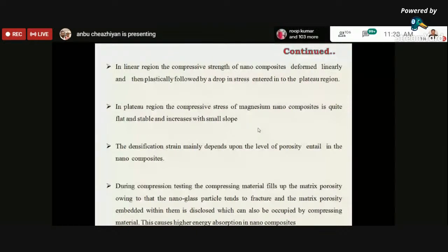In this plateau region, the stress remains constant. It is able to withstand the load transferred from matrix to the reinforcement. Finally, the nanoglass particles tend to break at this maximum strength, and due to that the stress level remains constant, and it appears as a flat and stable region. Finally, the densification strain depends upon the level of porosity in the nanocomposites.